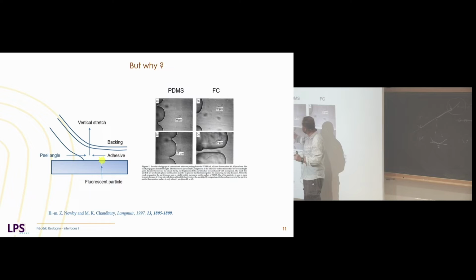So first answer, why is the slip important here? Well, where does the adhesion come from if I take a scotch tape? To some point, it comes from the dissipation in the adhesive layer, as already told, so that's the reason why it's important to optimize the viscoelastic and nonlinear viscoelastic properties of the adhesive. But if there is some slip, mainly you do not shear your adhesive layer. You take it as a block, and you don't consume any energy in the adhesive, so the adhesion is low. You need some adhesion at the interface in order to be able to deform the bulk adhesive, which gives you large adhesion. So at least here we understand why there is a difference between slip and no slip in these two cases.